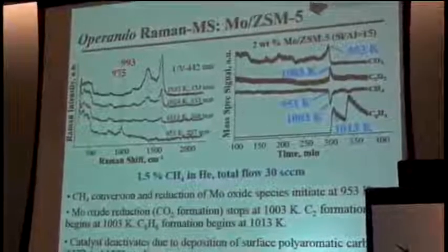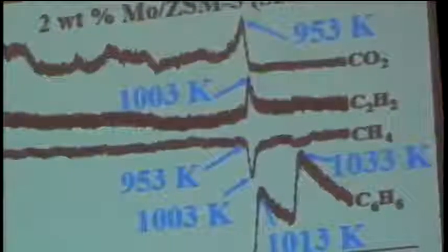Then, at higher temperatures, as we continue running the reaction, with increasing the reaction time, we deposit a lot of coke on the catalyst, and the catalyst deactivates rapidly. So from this experiment, and that has been confirmed with previous studies with EXAFS and XANES, that the working structure of the catalyst is not the oxide. It converts to carbide particles. So the composition changes, and from the atomically dispersed molybdenum, it actually forms larger carbide particles.